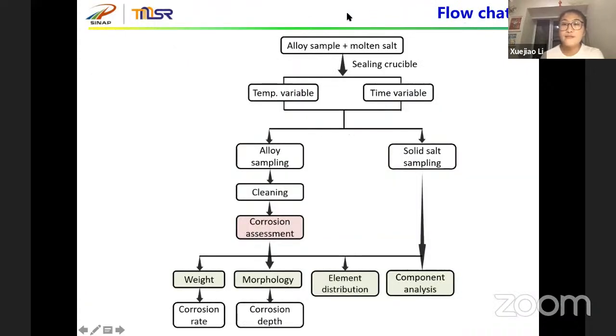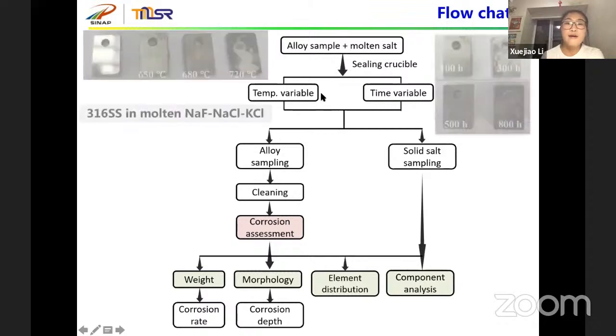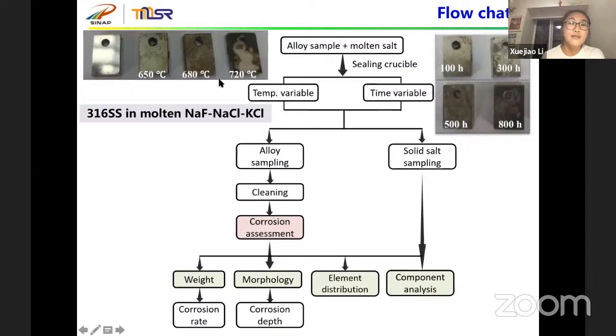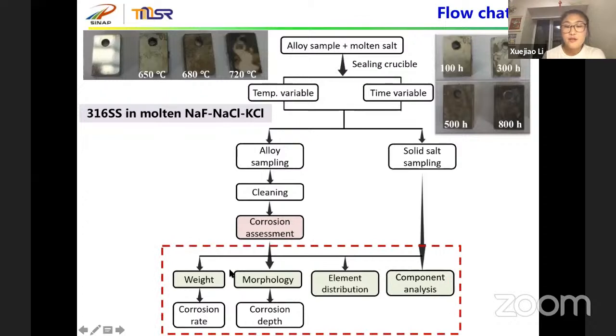This is the flow chart. The alloy sample and the molten salt are sealed into a crucible. Two variables are considered. One is temperature, the other is time. This picture shows stainless steel 316 in this molten salt. It can be seen that the corrosion became serious and the alloy changed from bright to dark as temperature and time increase. Furthermore, the weight, morphology, and element distribution of the alloy sample are examined to obtain the corrosion rate and corrosion depth.